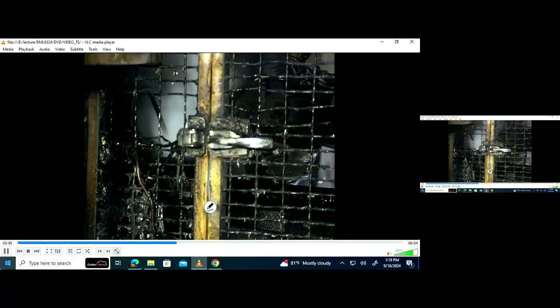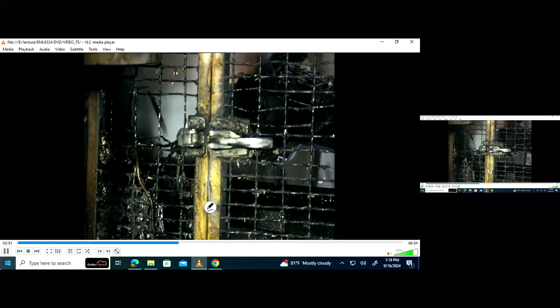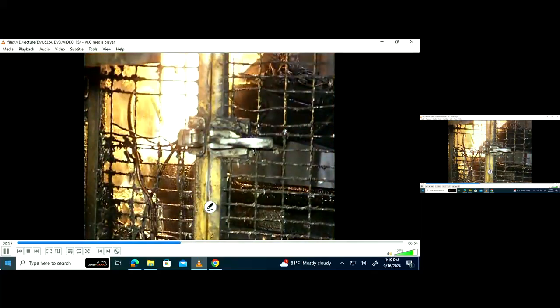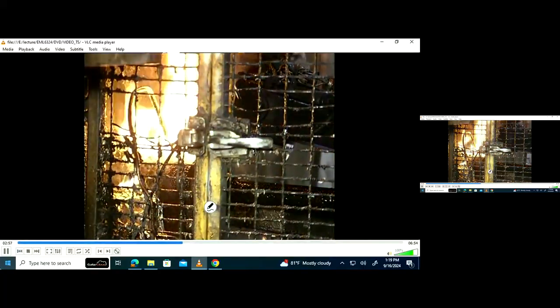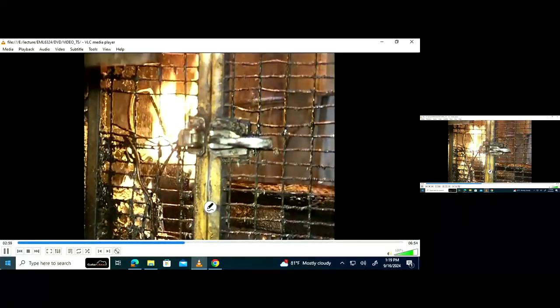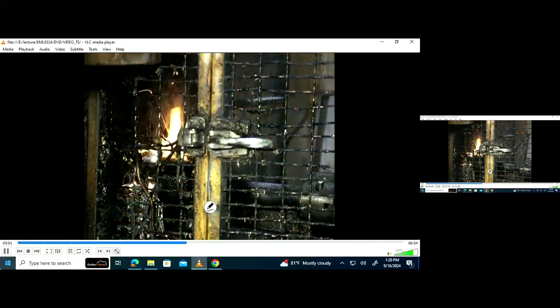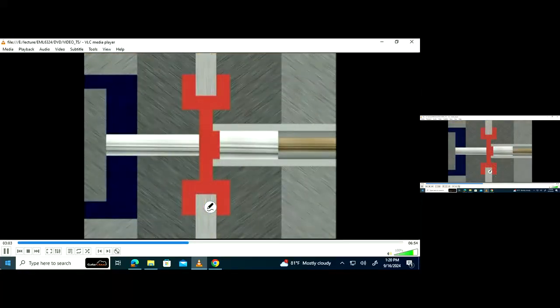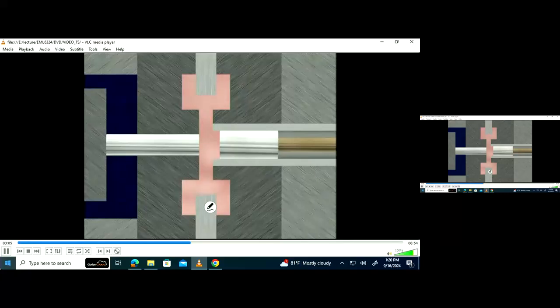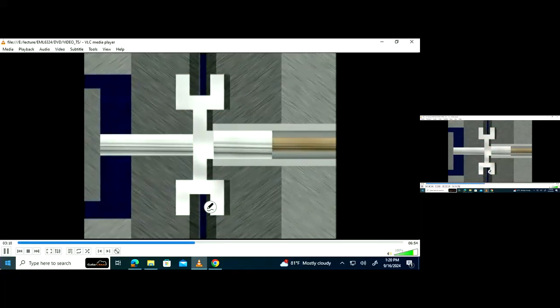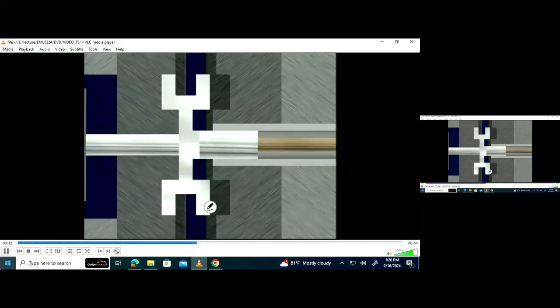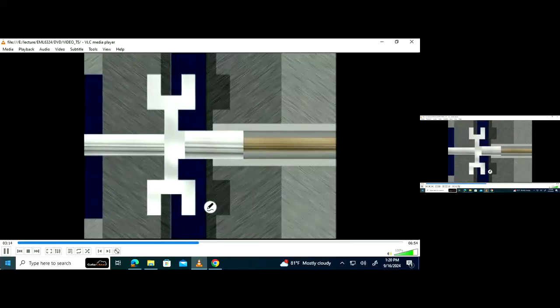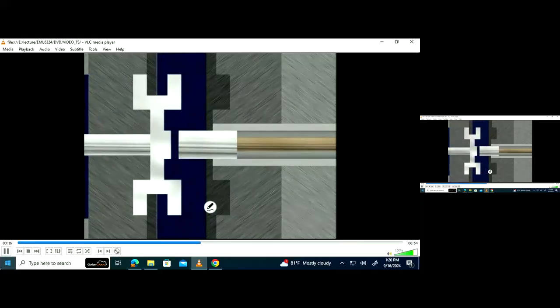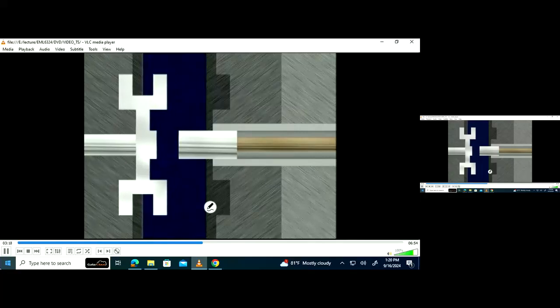Injection pressures may range to 10,000 pounds per square inch or 69 megapascals for aluminum and magnesium, although some machines can provide still greater pressures. After the metal in the die solidifies and the die halves are separating, the plunger thrusts forward, extending the plunger tip past the cover die. This pushes the biscuit that solidifies at the end of the shot sleeve, assisting casting release.